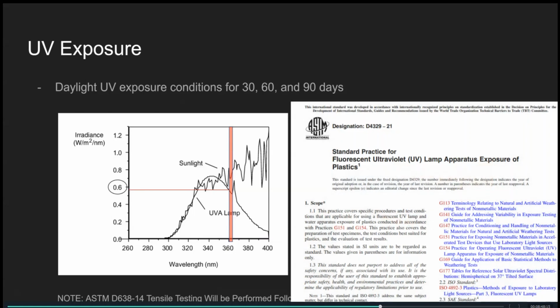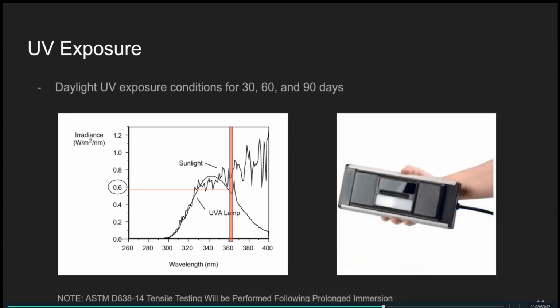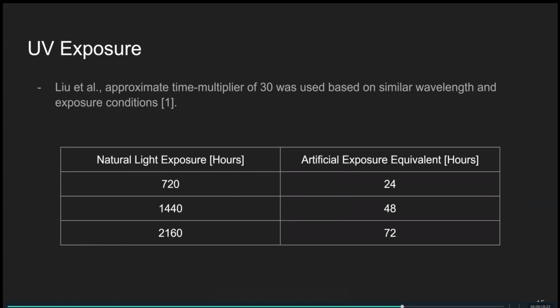And in addition to the fluid testing, Alex earlier mentioned UV exposure. Because these parts were cured using UV light, it was important to investigate how the material degraded if exposed to UV light for a long duration of time. Now, in order to simulate this, we were planning on using a UV light at around 30, 60, and 90 days. Instead of exposing the parts to direct sunlight for 30, 60, and 90 days respectively, we chose to use a UV lamp. The natural light exposure for 30 days is 720 hours, but that could be achieved by an artificial exposure equivalent of 24 hours via the UV light. So that same process is repeated for the 30, 60, and 90-day periods.